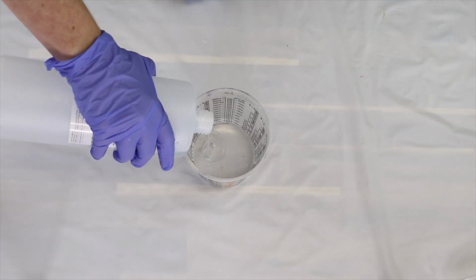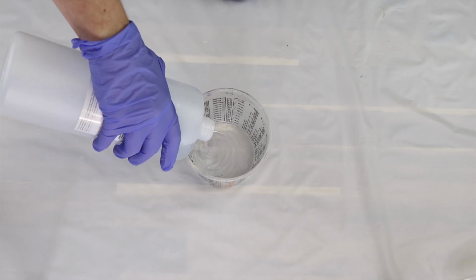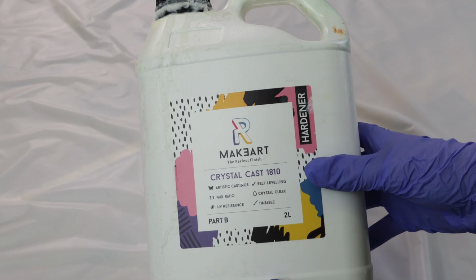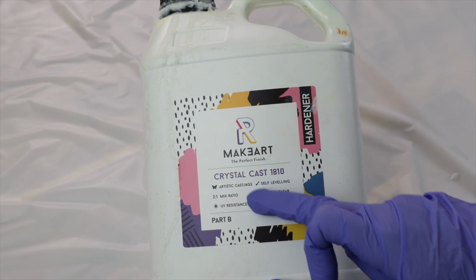Different brands can have different ratios, so do not just assume all casting resins are a 2-to-1, and always check whether they want you to measure out by volume or by weight. And that is very important to just double check that. Most casting resins are done by volume, so a mixing jug and just doing it in mils, but not all are. This one also says it's a crystal clear, it's a 2-to-1 mix, it's an artist casting, self-leveling, and it's tintable, which means you can add color into this if you wanted to. Those are all really important things to look for.